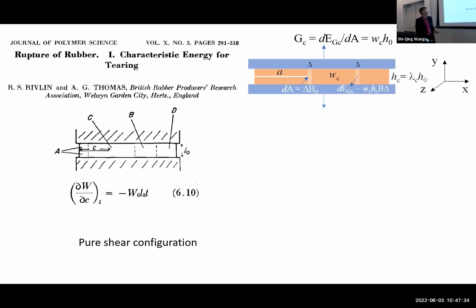I will actually not go through too much with you. There's another scenario. I showed you a single cut. There's another scenario called pure shear. This actually was the one driving me crazy, because it was so cleverly derived as a protocol. Basically, it says GC should be given by the work density times H. If my H is bigger, I have a bigger sample, so my work density only needs to be lower because this other term is constant. I was so mad with this result because this is truly a beautiful way to say it's an energy argument, right?